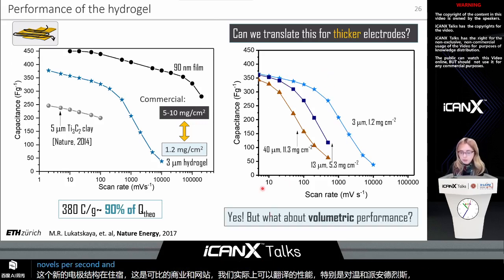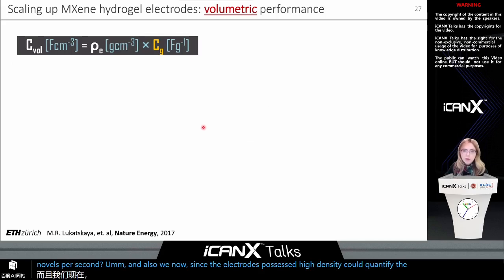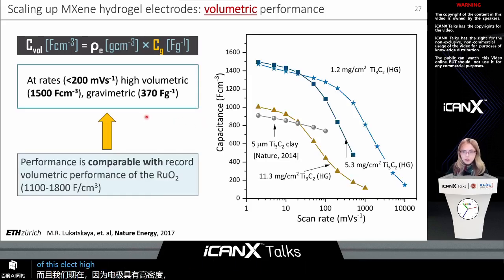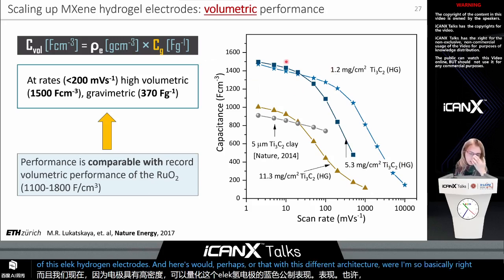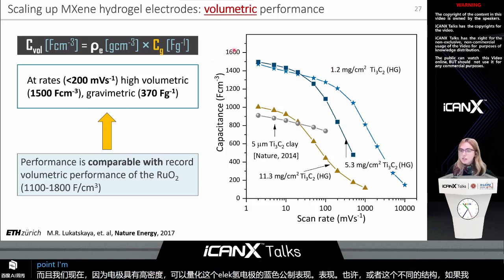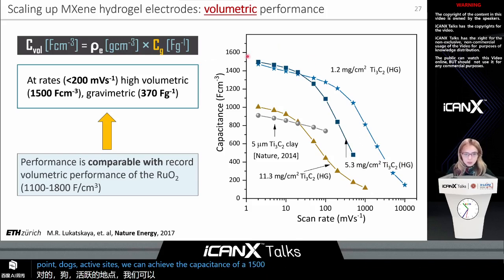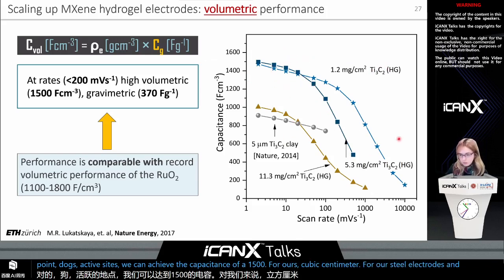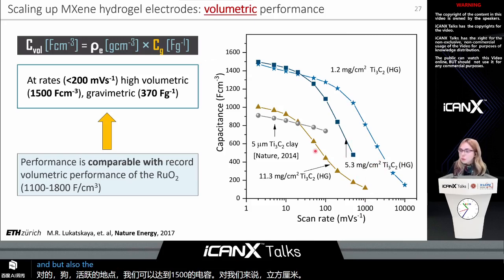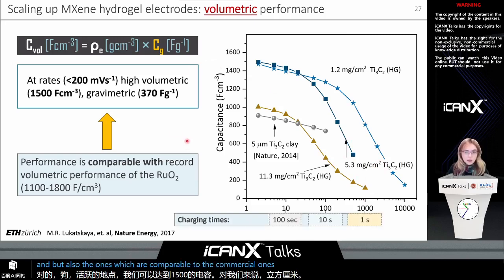And also, since the electrodes possessed high density, we could now quantify the volumetric performance of these hydrogel electrodes. And here's what we observed: with this different architecture, where ions are basically right at the redox-active sites, we can achieve a capacitance of 1500 farads per cubic centimeter for our thin electrodes, and also for the thicker ones which are comparable to the commercial ones. And here are just the charging times for your reference.